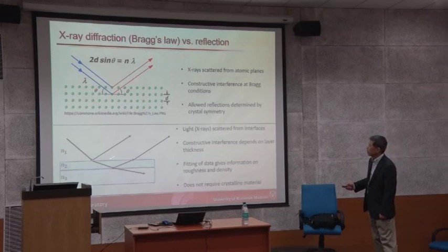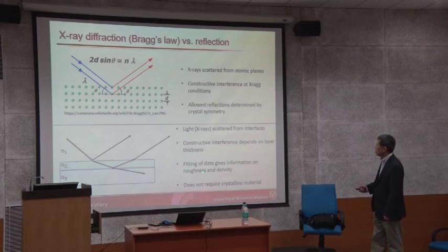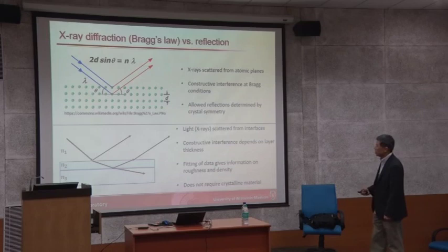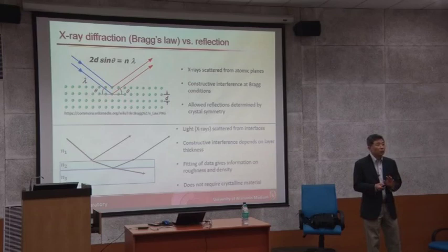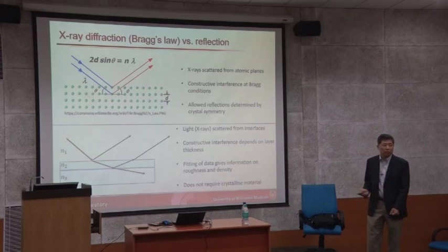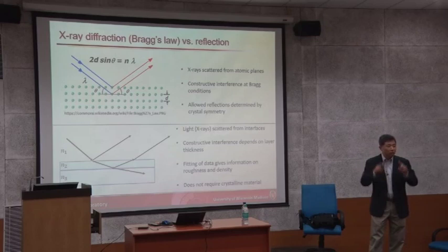When you go to higher angle, you literally see the Bragg peak. You have two components — the interference fringes and the Bragg peak. You use XRR — X-ray reflectivity measurement. Basically you have Bragg law X-ray scattering, and you're also scattering from the whole film. When you do this, you construct the interference from the film layer thickness. This film information measures a lot of things: roughness and density. This doesn't need to be crystallized — you can even use amorphous material, as long as the film is smooth.